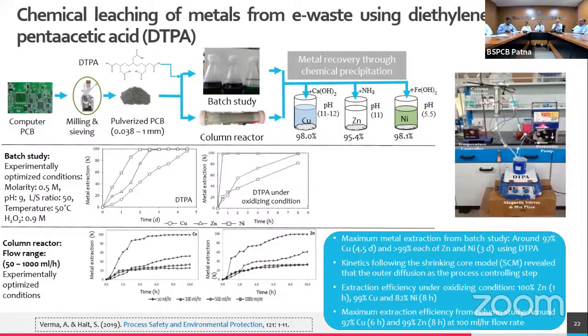Then we performed the experiment, and as you can see here, the metal extraction efficiency can be as high as 97% or 99%. The only issue is that since we are using organic acid, the time requirement is longer. If you use mineral acid, it can be achieved in, let us say, 4 or 5 hours, but this takes 4 or 5 days, or 3 days.